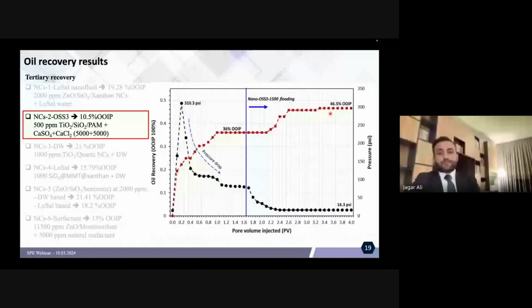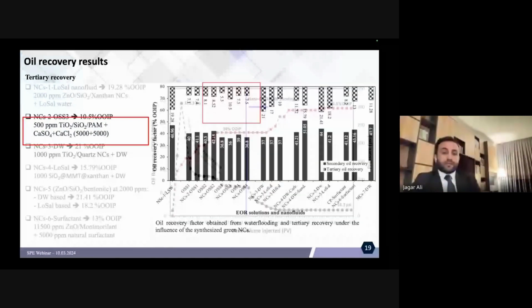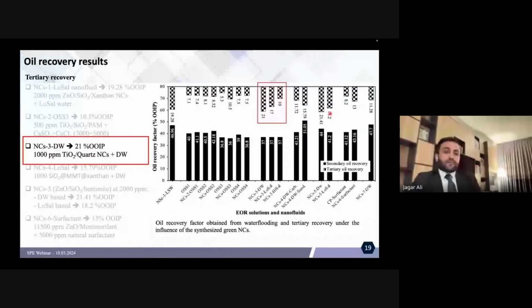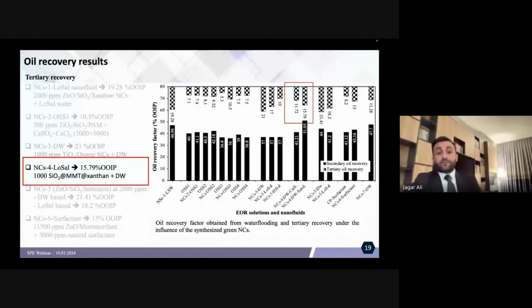And this is one example of the profile of the oil recovery and pressure during the oil displacement. So then we have the third one, when we used TiO2 quartz with distilled water, with mixing only 1000 ppm of the nanomaterial. With distilled water, it showed the best performance, which is around 21%. And this is the profile of the oil recovery for different oil displacement or core floodings.